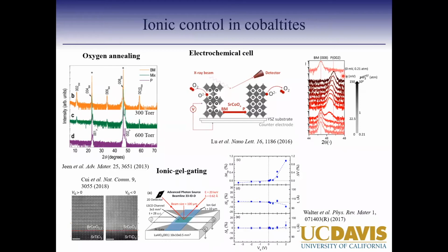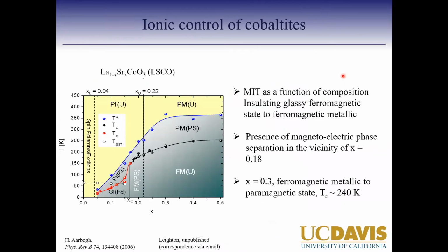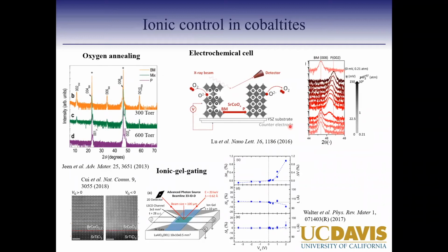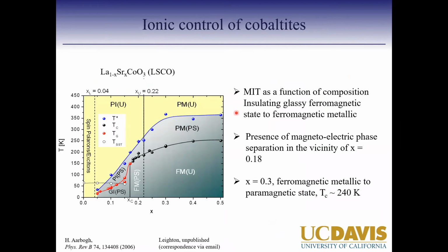So our collaborators recently looked at lanthanum strontium cobaltite, especially where perovskite is the ground state. The earlier examples are where strontium cobalt oxide, the brownmillerite, is the ground state. Using perovskite as a ground state is much more interesting because, with the choice of substrate, you can control the strain. So you can tune the perovskite phase much more nicely compared to a brownmillerite phase. This is LSCO, which our collaborators started fabricating as very nice thin films.